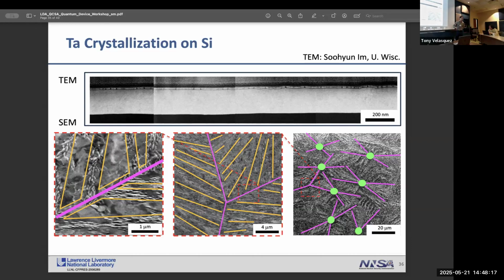You can make essentially amorphous tantalum. If you grow tantalum at low temperature, you get this beta phase that I was referring to, and that's an amorphous phase essentially. The unit cell is like 20 atoms or something. For the niobium tantalum interface, do you need the niobium to be crystalline?